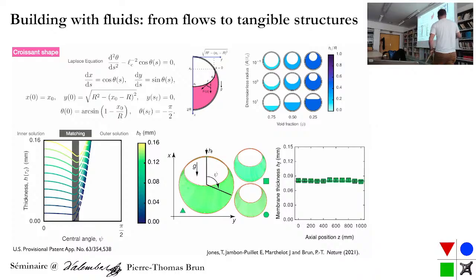And then we have this plot, which appears boring, but is very important. So the plot shows the thickness at the top as a function of the position in the tube. So that's a different tube. It's a very long tube, 1 meter. And what you see is that the thickness is actually 100 microns, plus or minus a few microns, and it's very uniform. And this is done without any fancy equipment. You just have to push with a syringe by hand. As long as you go far enough, you get this essentially for free. So it's a robust system.